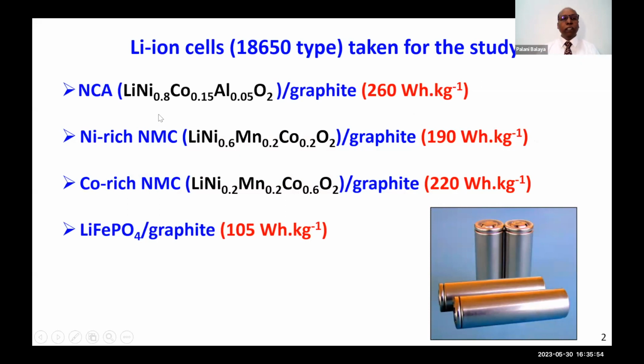Energy density is given. This is an oxide chemistry. There's nickel-rich chemistry, nickel-rich NMC 60, 20, 20, again oxide chemistry. Cobalt-rich NMC 20, 20, 60 versus graphite. The last one is a polyanion, lithium iron phosphate versus graphite. Lithium-ion LFP technology in short has a relatively lower energy density, but you will see that it has much better thermal stability as well as safety features.